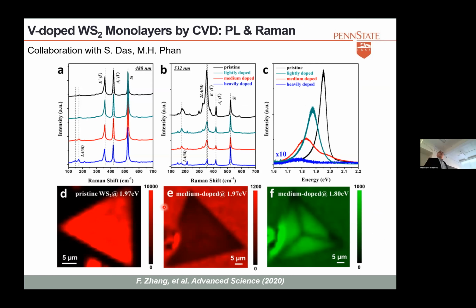I'll go quickly, because I don't have much time, but this is the pristine tungsten disulfide, right? This is the Raman spectra of the pristine tungsten disulfide when it's in resonance. This is with the green light, this is with the blue light, but the green light is resonant. The 2LA mode here is resonant. This is the LA mode here. But then you have the E prime mode, which is the in-plane mode, and this is the out-of-plane mode. This is silicon.